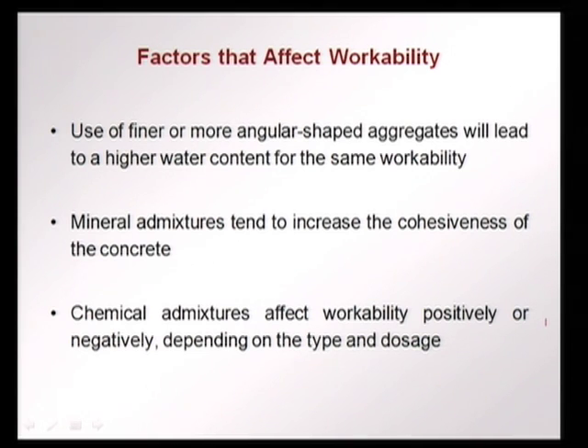In terms of the other components other than the cement and water, the type of aggregate or the shape of aggregate will also affect the workability. Use of finer or more angular shape aggregates will lead to higher water demand, and if this higher water demand is not met, then the workability drops. For the same workability, if your aggregates instead of being rounder are more angular, that means more water or cement paste would be required for the same workability. In terms of mineral admixtures, depending on the type of mineral admixtures, we will have different workability. Generally the mineral admixtures are fine materials, therefore they increase the cohesiveness of the concrete. The concrete has less bleeding, however it becomes more sticky.